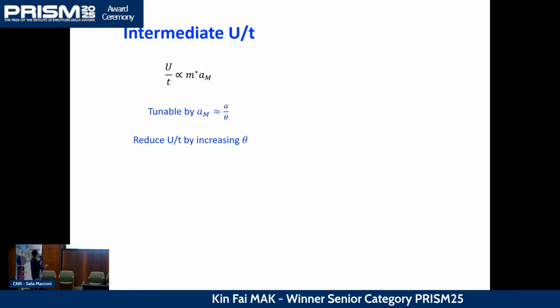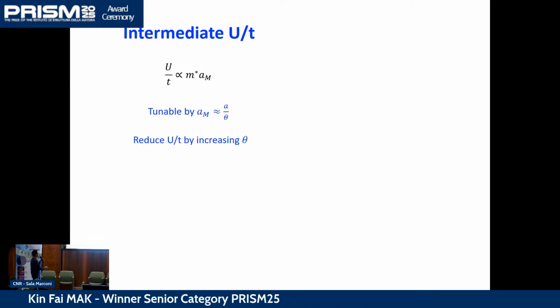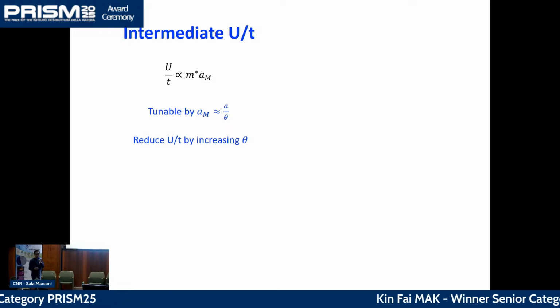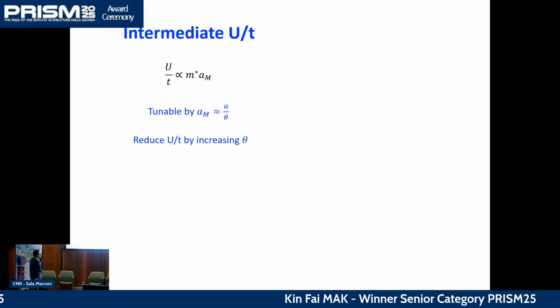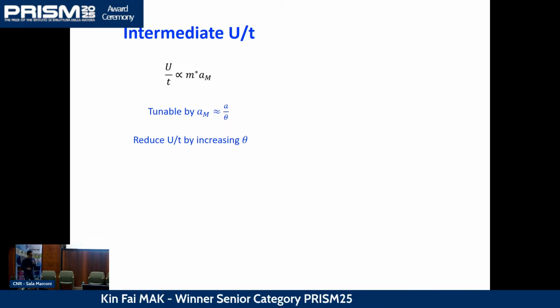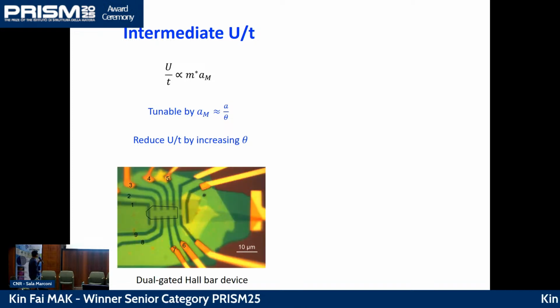And so to reduce the ratio, we actually want to reduce the Moiré period. And the Moiré period is proportional to 1 over the twist angle, so you want to increase the twist angle in the system. But we can do that in our material, right? You can continuously tune the twist angle without a problem. And so this is actually a device.